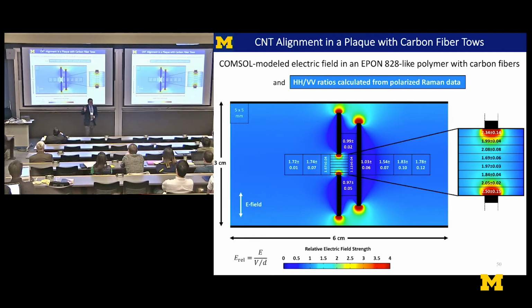Interesting thing, which in retrospect I should have realized from the beginning, carbon fibers are electrically conducting. By definition, electrical conductors can't sustain a voltage gradient. What that means is along the length of the fiber, near it, I don't have a voltage gradient. What that also means is, as a COMSOL model, I get a harder gradient right at the edges. Well, that's where you want to, in fact, have the increased load transfer. So it turns out nature is in the right direction.